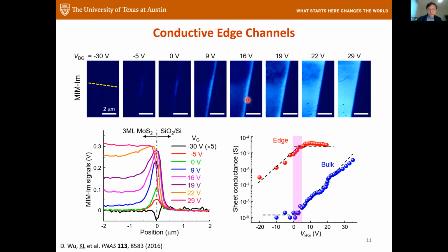Right? So the physics, I would guess you already know what's happening. It's just some dangling bonds, especially in one particular, I forgot, armchair or zigzag edge. If one calculates the in-gap states, you'll see at the edge, these dangling bonds are contributing some kind of in-gap states. So when you use a gate to move the Fermi level up, at some point it's going to first hit these in-gap states.